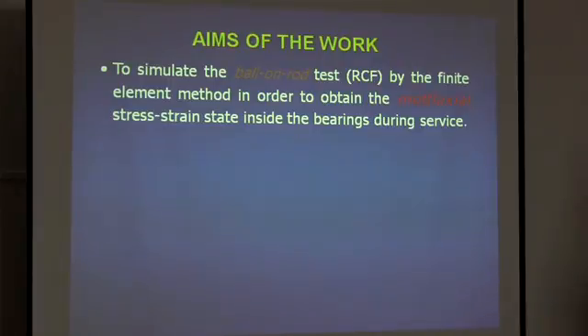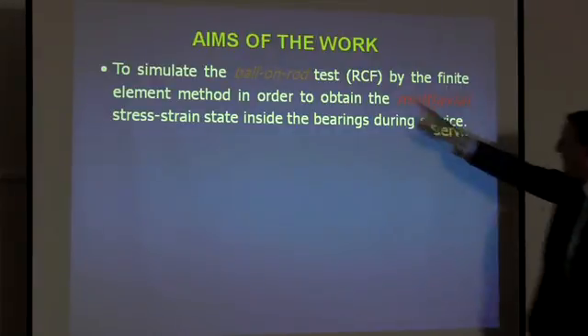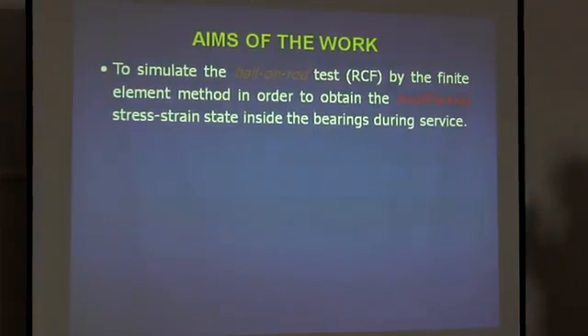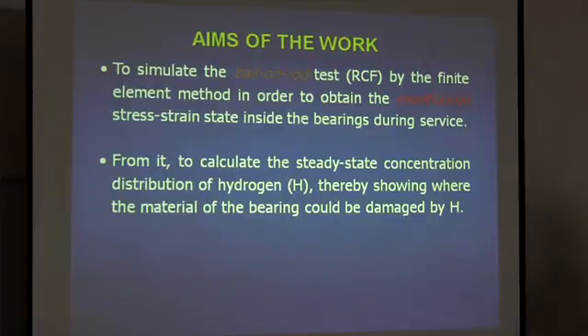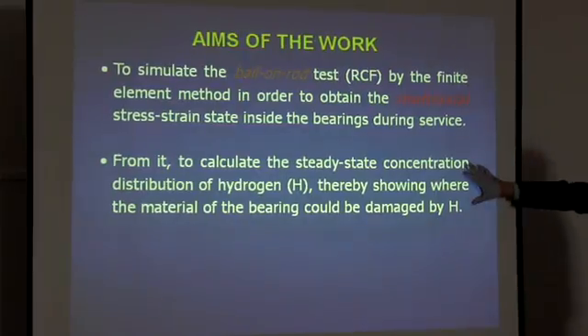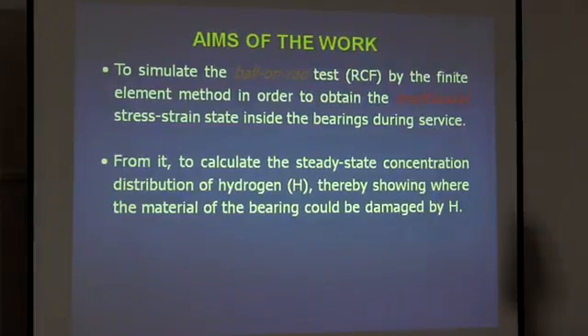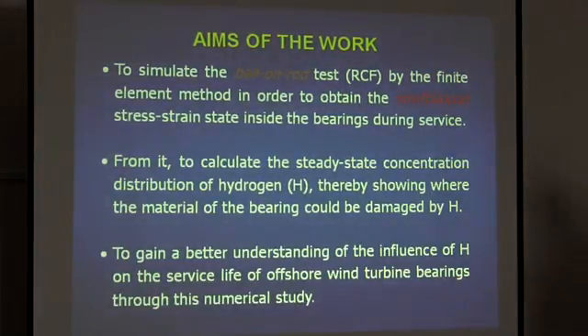The aim of the work is to simulate the so-called ball-on-rod test, three balls rolling over a rod, a cylinder: hydrogen-assisted rolling contact fatigue. We have to simulate by the finite element method in order to obtain the multiaxial stress state inside the bearings during service. From it, first of all, stress state, mechanical analysis, and from it, the steady-state concentration distribution of hydrogen, chemical analysis. This is the mechanical part, this is the chemical part. Thereby showing where the material of the bearing could be damaged by hydrogen, the places where hydrogen diffuses for a long time. And thus to gain a better understanding of the influence of hydrogen on the service life of offshore wind turbine bearings through this numerical study.